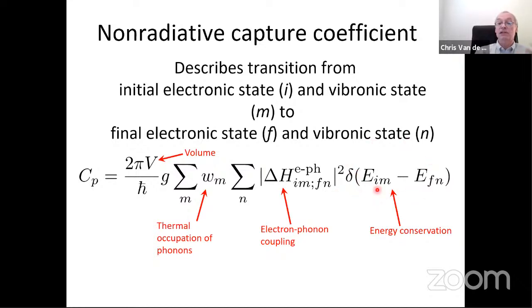There is a delta function that says that the energy in the system needs to be conserved. The energy of the initial and the final states need to be the same. And if you integrate this energy delta function over all possible states of the system, you essentially map out the density of states. So this is Fermi's golden rule, and the quantities that occur here can be explicitly calculated from first principles. The electron-phonon coupling, the band structures, and the phonon properties that give these energies, etc.